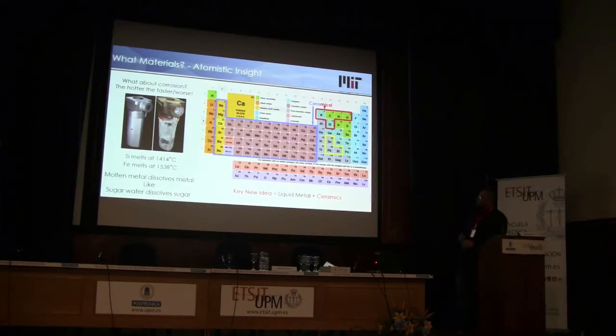Now, the reason I bring this up is because essentially corrosion boils down to the idea that there's some group of atoms that would like to interact chemically and form a stronger bond with something else, or possibly release some gas or something that would have a lot of entropy with it, and so the reaction will be favored as you go to high temperature. What we found, though, and I think we'll put this in the book chapter, is there are interesting regimes of stability. So typically, when you talk about corrosion, people are thinking about metals below about 1,000 degrees C. Generally speaking, the hotter you get, the worse the corrosion. It just accelerates the kinetics.